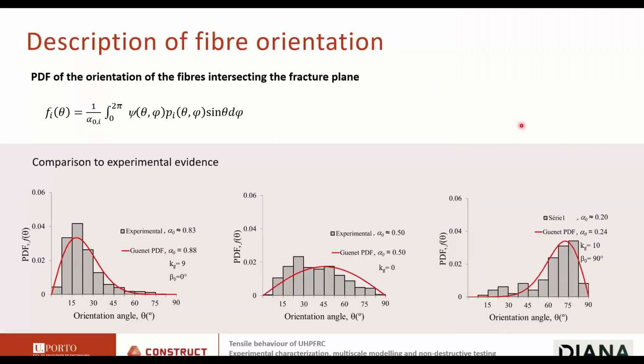Also important, as we will see, is another concept, which is the probability density function of the orientation angle of the fibers that intersect our crack. Not all the fibers in the volume, but the fibers that intersect our crack. So it can be shown that it's given by this equation. And I show you here some experimental evidence that helps validate a little bit more the probability density function that we are using. So these histograms were obtained from image analysis of polished surfaces of UHPFRC specimens, and the red curve is the theoretical value. And we try to fit the alpha value in our theoretical curve to the alpha value that we got in the experiment.